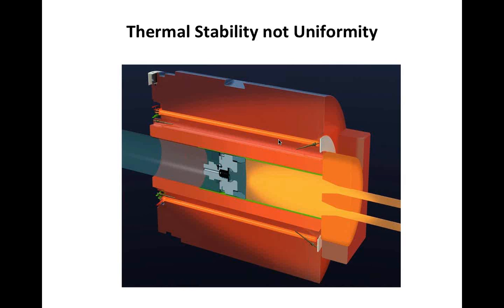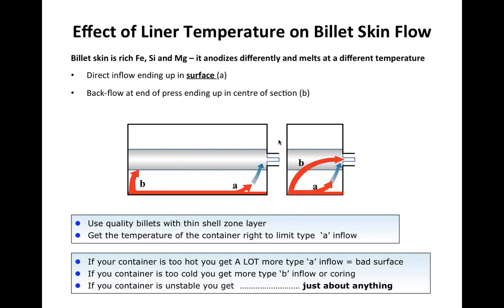So the key for the container is the thermal stability of the container, not the thermal or temperature uniformity. We've discussed a lot about temperatures, and the temperature of the liner will have a very dramatic effect on the skin of the billet flow. If the liner is hotter than the billet, you will have a type A inflow. If the temperature of the liner is colder than the billet, you will have a